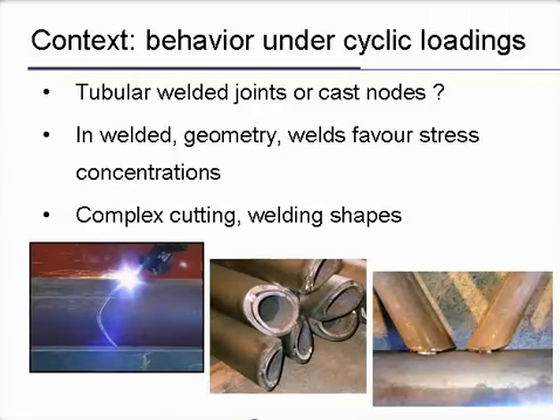Why do I speak about these cast steel nodes? Well, one thing I've worked on is, of course, the behavior of these under cyclic loading. And effectively, the question is always, is it better to use tubular welded joints or cast nodes? So I will show you some things about this. In welded joints, the geometry is not so optimal, and you favor stress concentrations, so in fatigue it is not so good. Also, you have complex cutting and welding shapes, which is not the best thing, so why not go to cast steels?